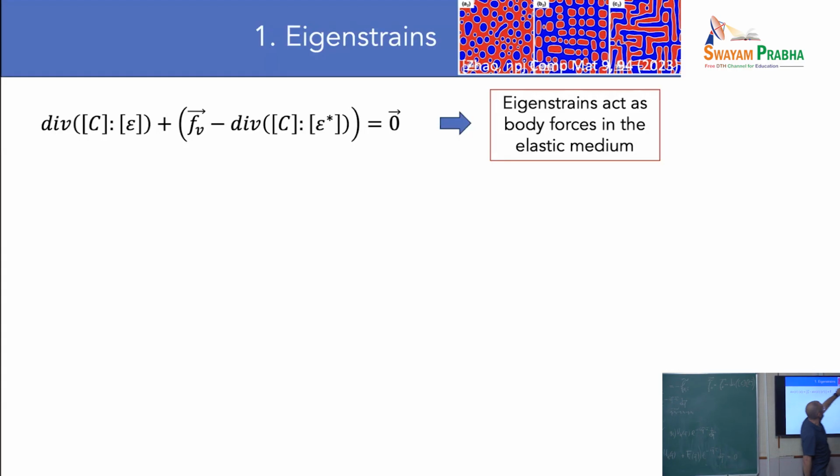So you start here basically with circular precipitates, and they become elongated because of the elastic cost. The eigenstrain inside these precipitates is not just a volume change. There's a tetragonality. We're going to talk about it later on.